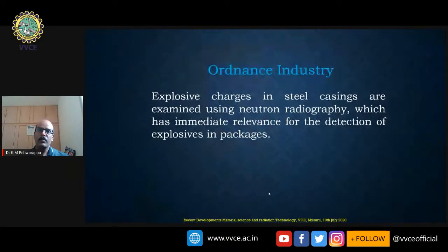But particularly neutron radiography is very helpful in detecting explosives, because the explosive contains only low Z material, and the neutrons get highly attenuated in the low Z material, hence it gives a very high contrast and also very good quantification of the material present in that case.